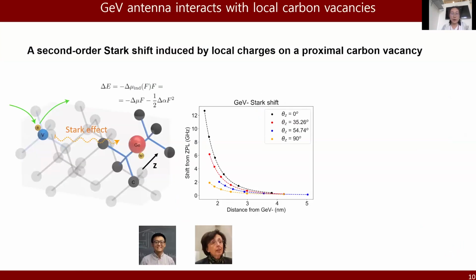Now we need to experimentally study the antenna effect from the GeV. If we only consider the field enhancement, I would say the GeV is not a very unique antenna system, because there should be many other atomic dipoles that can have coherent transitions and can potentially be used as antennas. But in most cases, those atomic dipoles are within a solid state environment, and when they generate a near field, it's experimentally difficult to detect such a near field.